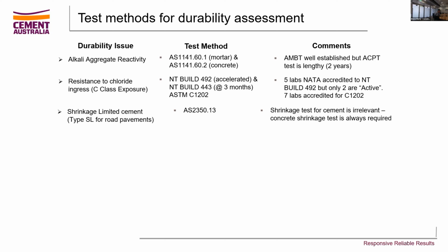Okay, moving on. The shrinkage of concrete is a perennial issue with all concrete mixes. And historically, some specifying bodies have tried to limit the shrinkage of concrete by placing restrictions on the shrinkage of cement. And there is an Australian method for this, AS 2350 part 13. But really this shrinkage test for cement is irrelevant. And it puts constraints on cement producers to produce economic general purpose cements. Because at the end of the day, the concrete always has to pass the shrinkage test. It's not the cement that has to pass the shrinkage test, it's the concrete mix in question that has to pass the shrinkage test. Which brings me on to the next test.